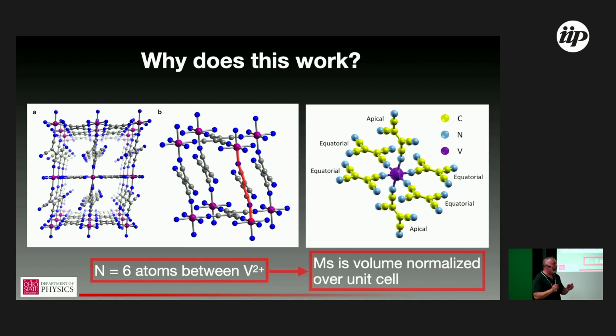So maybe one way to say it, I can't remember who off the top of my head. If I think of a pure Heisenberg ferromagnet, they're the same thing, right? So you're saying there's a different type of... Could I take another shot at this, which is the exchange stiffness has a volume component to it, right? So it's essentially a continuum model where you've smeared everything out evenly over the system, and that's a total failure for this, because the spin active regions are maybe 100 times smaller in volume than the total volume in the unit cell. And so what you should use is the volume that's well occupied by electron density. And if you were to use that kind of thing, then you would get a much higher effective number.